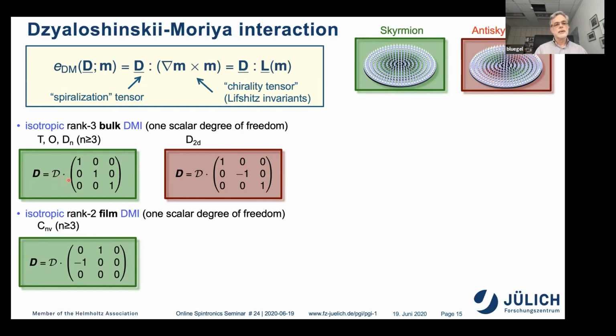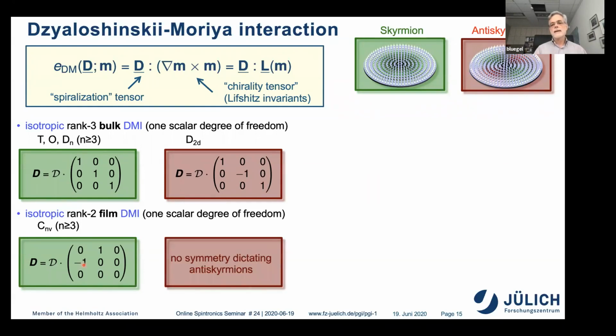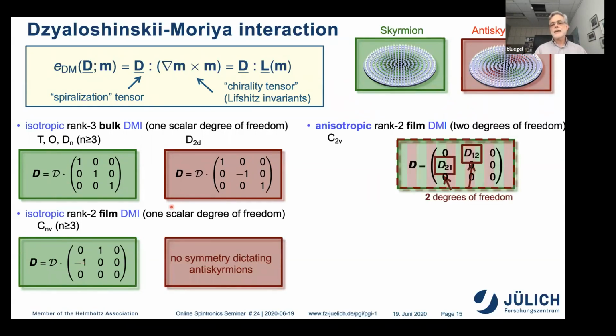If you look now at this spiralization tensor, we discussed the isotropic one, rank 3, the tetragonal and the cubic one, the D2d one. Then we have the film ones, which give you the Néel type structure. But what we found out is that there is also a symmetry group, C2v, typically (110) surfaces, or lower symmetry, where something fundamentally changes. This Dzyaloshinskii-Moriya interaction is no longer described by a single scalar quantity, but by two independent quantities. We call that not the isotropic, but the anisotropic Dzyaloshinskii-Moriya interaction.